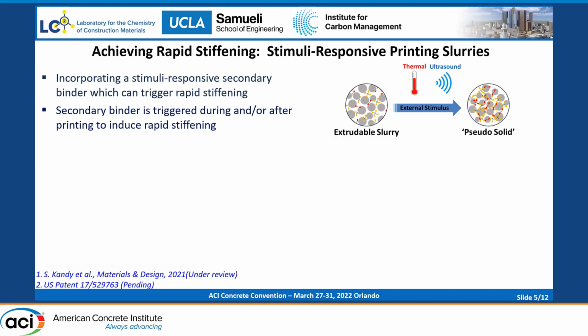Here, we are talking about rapid stiffening. So exclusively depending on the hydration will be very challenging because hydration kinetics is relatively slow. So the approach we used is incorporating a secondary binder in the suspension, and we can induce rapid stiffening by triggering those secondary binders which are incorporated in the suspension.